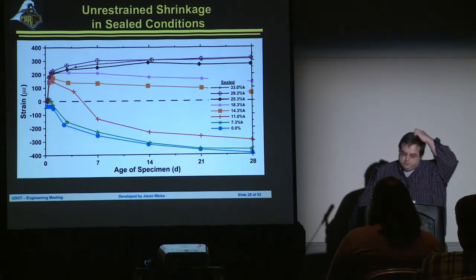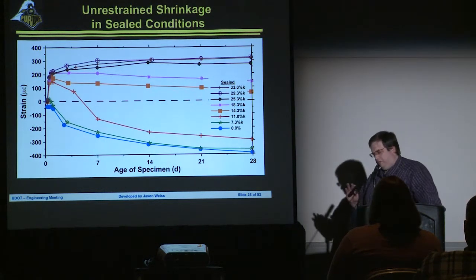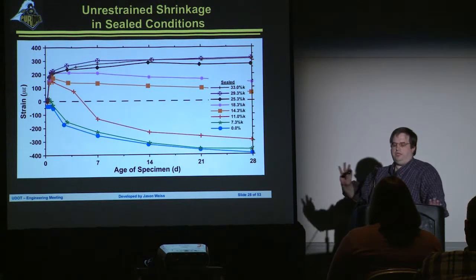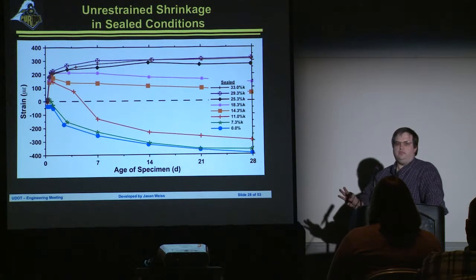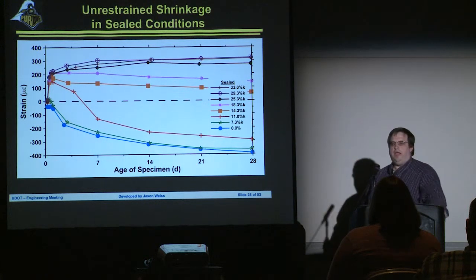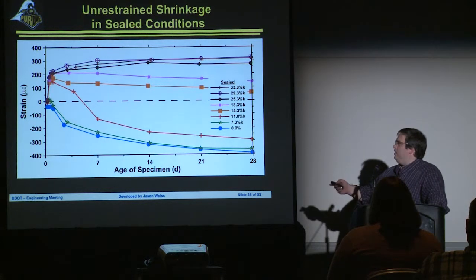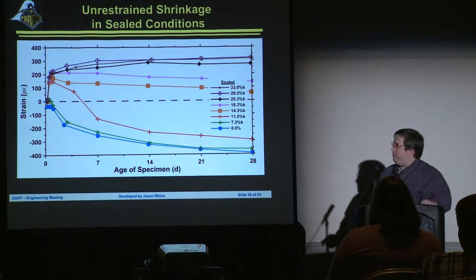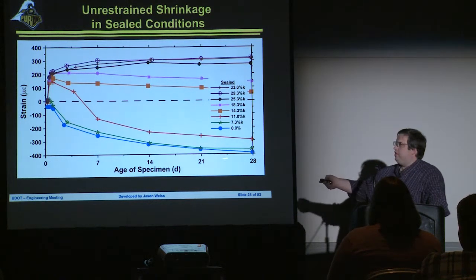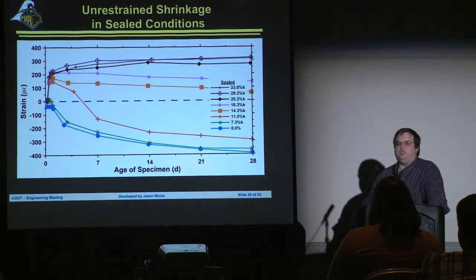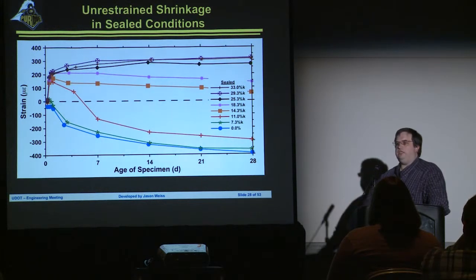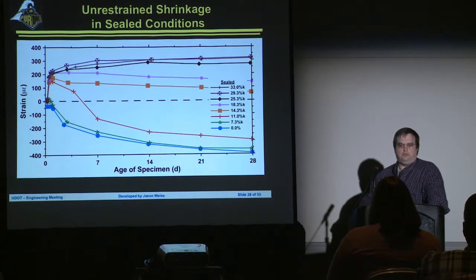We can also measure these in sealed systems and do other types of things to measure the overall length change. Now, there's a lot of data on this graph, and I will promise if anybody wants to see data, I will be more than happy to send 3 or 4 of the most voluminous theses I've ever seen in my life, and I will be happy to talk you through any questions you have on these. I don't want to get hung up on all of the different numbers and what everything means. Here we've essentially got free shrinkage. The blue is a conventional mix that we got about 400 microstrain of shrinkage after 28 days if the system is completely sealed. So you've applied your curing compounds perfectly, you've got plastic sheet on top of it, you've got 400 microstrain of shrinkage after 28 days.